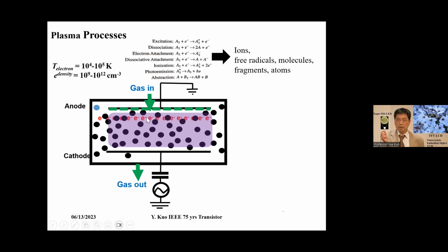And during the process, light is emitted. So we see the plasma light emission. We can take emission spectroscopy, and from emission spectroscopy, we can identify the major components in the plasma process. Basic plasma process includes two components. One is charged species, such as ions. The other one is neutrals. It's very complicated because neutrals can be molecules, atoms, fragment molecules, free radicals. Those highly reactive elements are responsible for the thin film deposition and etching, which is different from conventional chemistry. So in this process, we are talking about non-equilibrium thermodynamics. The conventional chemistry we learned, the equilibrium thermodynamics, does not apply here because a lot of quantum reactions occur. So this is the chemistry part.